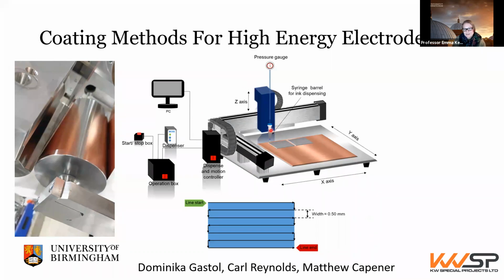What we were doing was using a syringe dispenser to make patterned electrodes. So we could syringe out, almost like 3D print, our electrodes with very little waste in a structured design. And this is one example of a design where we could create little valleys and troughs in between our electrode as we coated it, at the same coat weights that we had for our slurry cast coating on our reel-to-reel as well.